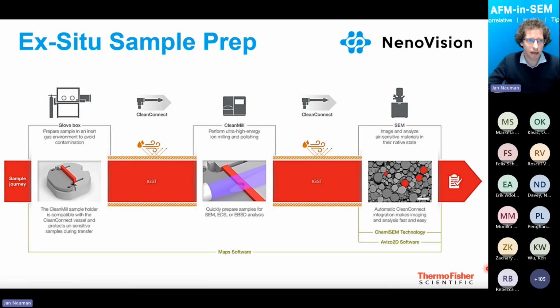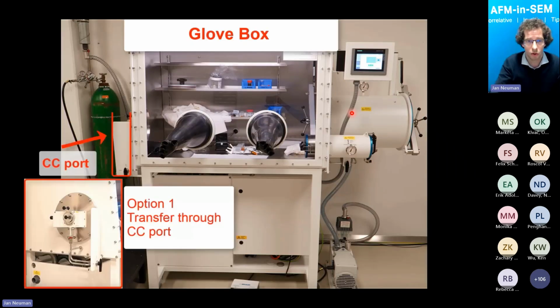For the ex situ sample preparation, we of course start in the glove box to avoid any air exposure. In the glove box you can do the cycling experiment, etc. Then you can use a so-called Clean Connect transfer, where you can, without any air exposure, transfer the sample into the Clean Mill. It's a product from Thermo Fisher doing the broad ion beam milling to make a cross section and prepare the sample. Again, use a Clean Connect transfer and directly move the sample into the electron microscope, which is already equipped with the AFM. This workflow we can also show you in the video.